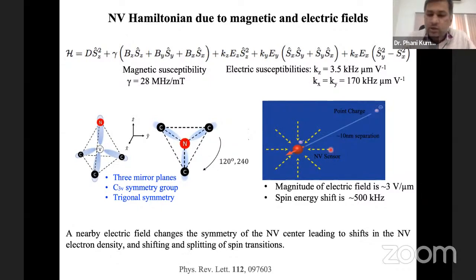This diamond lattice can also have static charges or fluctuating charges nearby these NV centers. Let's say that we have a point charge around 10 nanometers separated from this NV center. It exerts an electric field of around 3 volts per micrometer or so. This is the magnetic field term, the Zeeman interaction term, and this is the term in the Hamiltonian which describes the interaction of the NV center with the electric field.